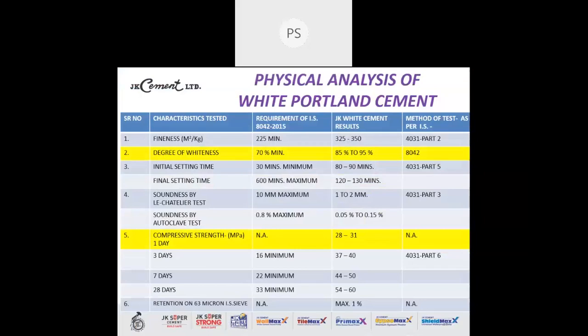The next slide is the physical analysis of white Portland cement. All of the points are more or less the same except for point number 2 and point number 5. Now we look at point number 2 first, the degree of whiteness. The degree of whiteness requirement as per IS code is 70% minimum. The whiteness of white Portland cement should be minimum 70%. And how is it measured? We'll see in the next slide. Now, JK White cement has a range of 85 to 95% for the degree of whiteness.